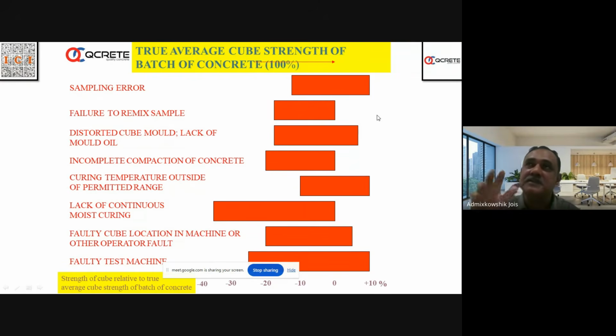So you have to invest a lot of time and then spend a lot of money also to convert that from an apparent issue to an acceptable cube strength. So here, sampling error. If the sample is not taken properly from the truck, then it may lead to a positive swing or negative swing. Failure to remix the sample will be negative, which is about 18 to 20% down.